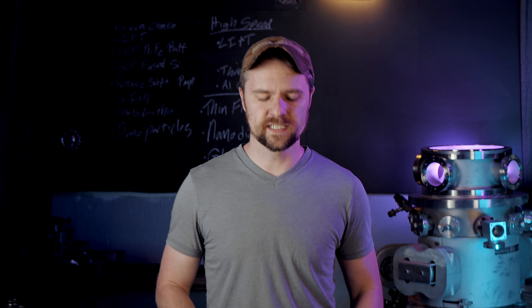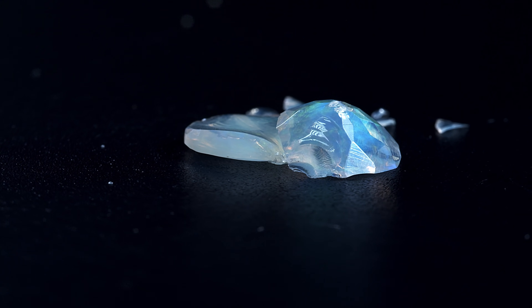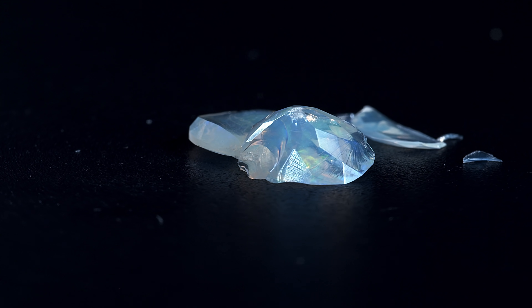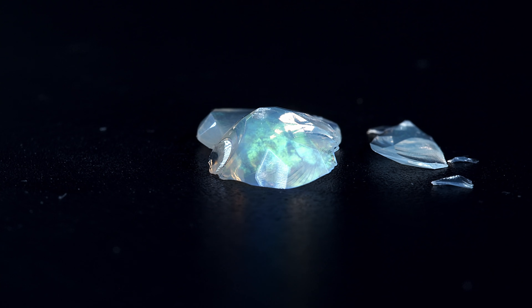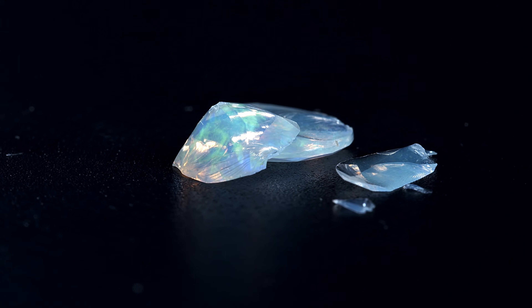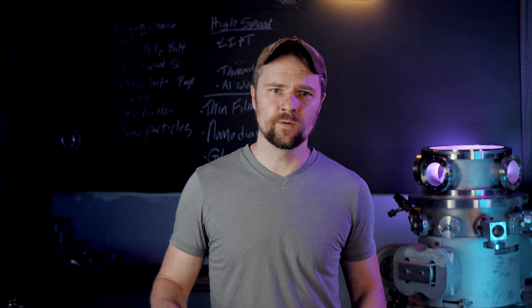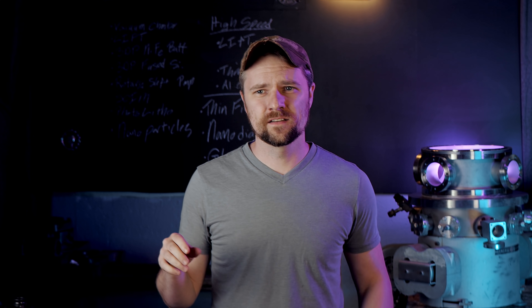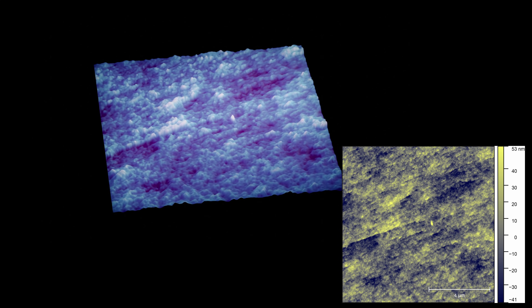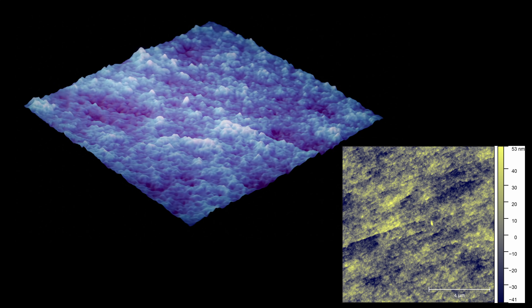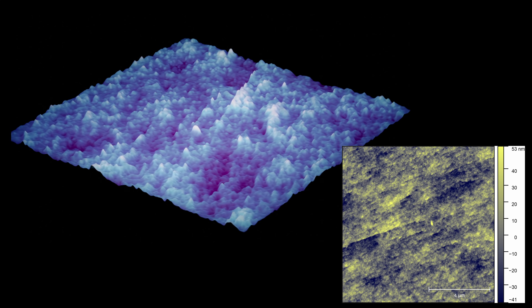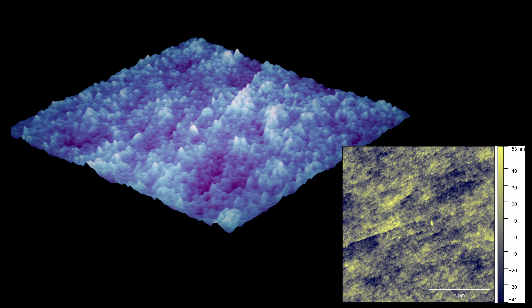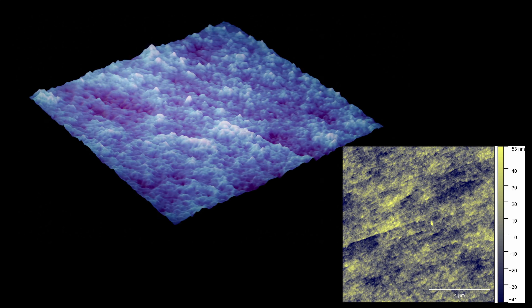I wanted to see the nanoparticles, and we weren't going to see that on the polished and ground faces. So I sacrificed one of the opals and broke it open for your viewing pleasure. The break was actually surprisingly clean — I was expecting it to crumble since it's based on little nanoparticles compressed together, but it sheared at a pretty nice angle, which made it reasonably easy to scan. Luckily the inside started to show some of the nanoparticles I was hoping for. Starting from a relatively large scan of 10 by 10 microns, you can see it's a pretty rough surface with a lot of the spherical particle nature we were hoping for, but despite looking rough it's actually still pretty smooth.